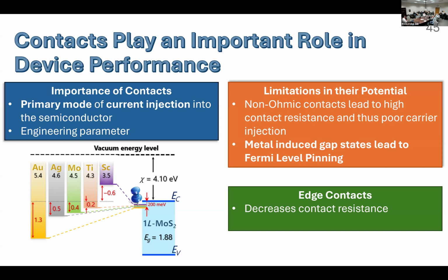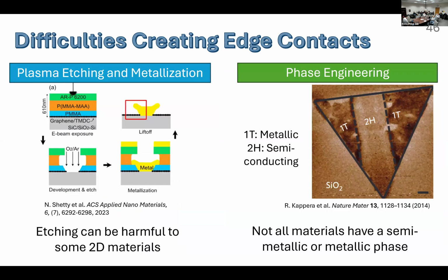One method that scientists have tried to use to overcome this limitation is incorporating the use of edge contacts. So in this case, the contact is done selectively on the sides of our 2D flake instead of on top and on the sides. However, there are difficulties creating these edge contacts. The most common methods are using plasma etching and metallization, as well as phase engineering.